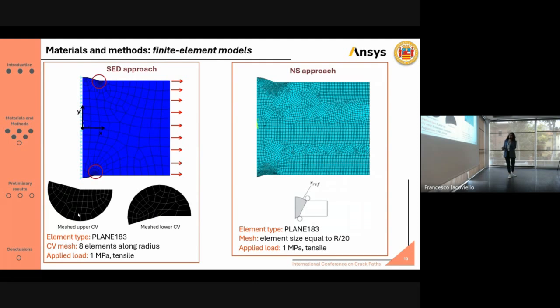Concerning the strain energy density approach, in this case, we know that the control volume needs to be considered and so needs to be meshed. In particular, according to literature, this control volume has a radius of 0.28 millimeters, and there are 8 elements along the radius.